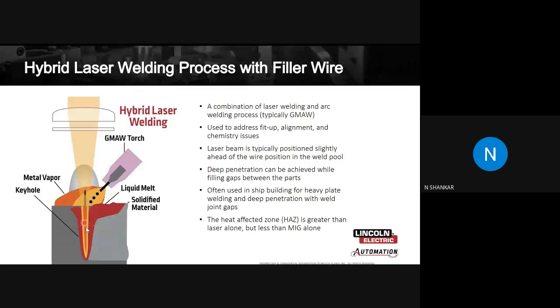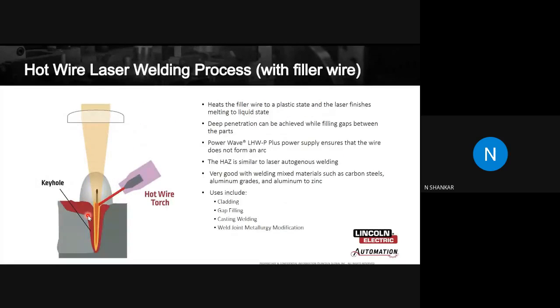it will be much less than GMAW alone. It'll find extensive use in shipbuilding applications for heavy plate welding and where deeper penetration is required with huge weld joints. So this is the area where hybrid laser is applied. You can have hybrid laser with a hot wire process where you can have the wire coming in preheated. That means you have a much better deposition in comparison to a conventional hybrid GMAW process.